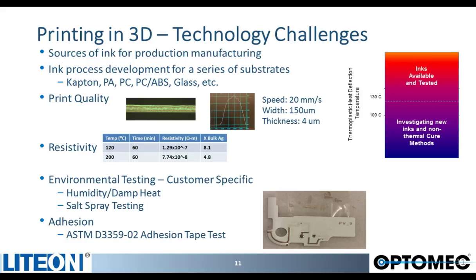We need to ensure the best print quality for line definition, consistent thickness, and the right process speed. And for antenna functionality, we need good conductivity for the sintered trace. The challenge again has been the low temperature resins. The environmental tests are quite harsh for a smartphone application, with each customer having a different set of standards.